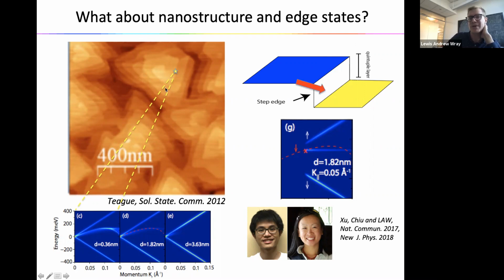So if we could zoom in on regions that have dense steps, or if the beam spot were down to 20 nanometers, so we had enough of a signal from one step, we could generically resolve emergent electronic structure features from nanostructure like this.